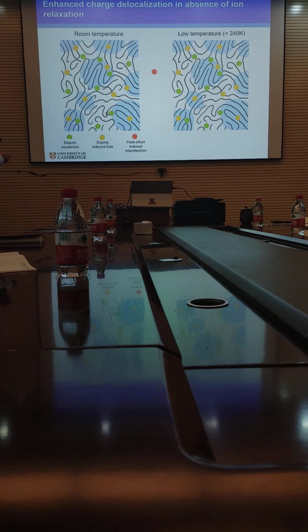The green dots are the counterions. The orange blobs are the electronic charges that we induce. So that's the system that we start with. And now we add an extra hole into that system with a field effect gate. There's no extra ion going in because it's a field effect gating experiment.